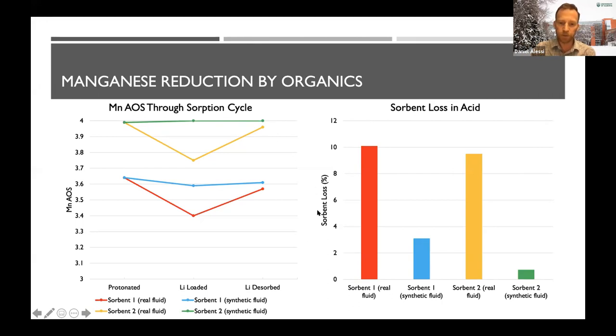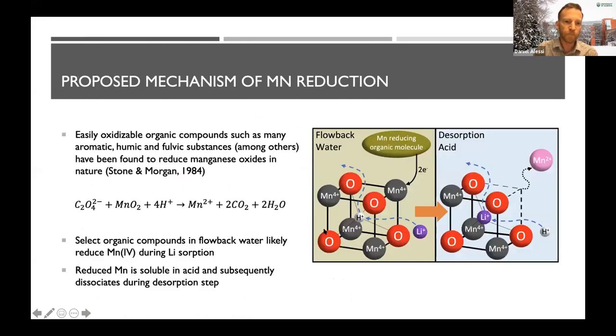So showing you the results here again with sorbent loss, and we see again with the example we were talking about, there's your 9% loss in the real fluid. In the synthetic fluid, less than a percent. So our proposed mechanism, if you look into the literature for soils, for example, there's a lot of literature about how aromatic substances, humic and fulvic acids, so these organic molecules, readily reduce manganese.